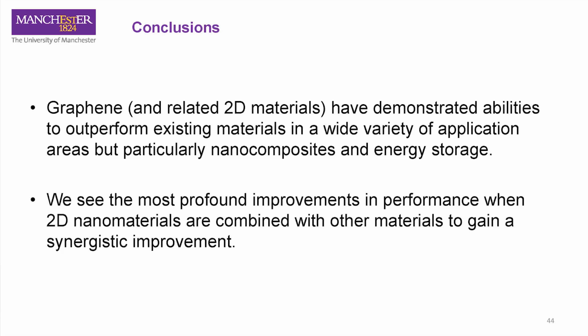So with that, hopefully that was not too fast. Hopefully I've summarized here that graphene and also the other related 2D materials have a lot of amazing abilities, but it's really the combination of them that makes them stand out. So it's not when you add just one material, it's when you add multiple materials together, that synergy. But also, you need very little of these materials. For a lot of the applications, the optimal loading that you need is less than 1%. So even if graphene is expensive, you only need a very small amount of it to get pretty significant benefits out of that, which is why we're seeing it commercialized so much, which is why tomorrow you'll hear lots of companies that already have a lot of products out there that are using it.